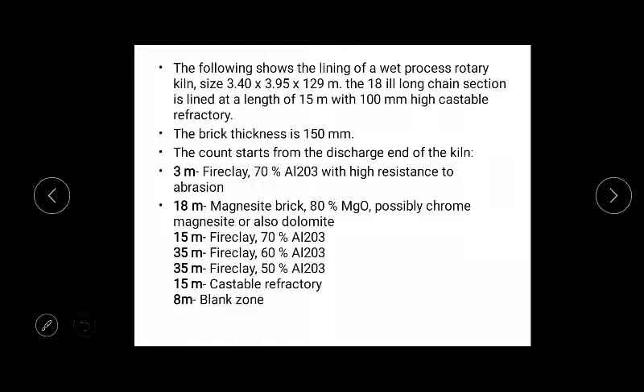Another set of refractory bricks which can be used in a rotary kiln is shown. The following shows the lining of a wet process rotary kiln. So here you were seeing a dry process manufacturing where we are using preheaters. When we are using a preheater, the length of the kiln is very short and the material which is entering the rotary kiln is at 800 degrees Celsius.